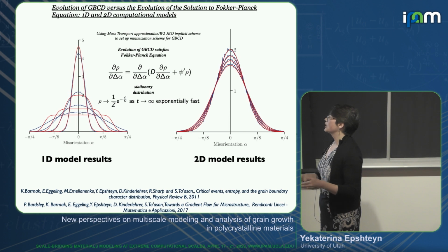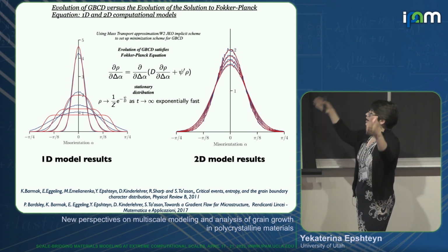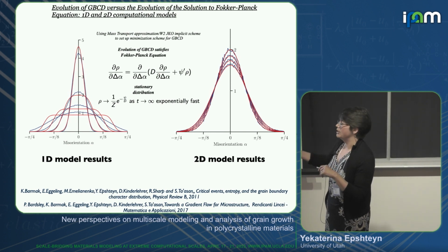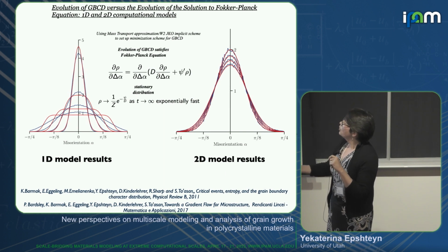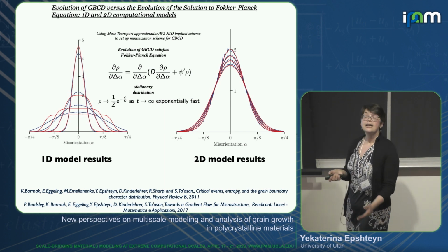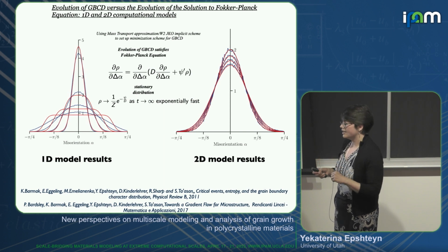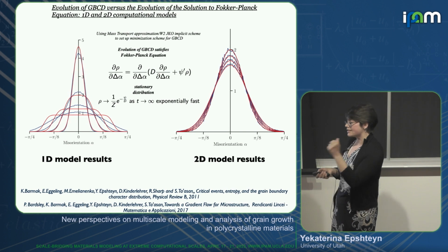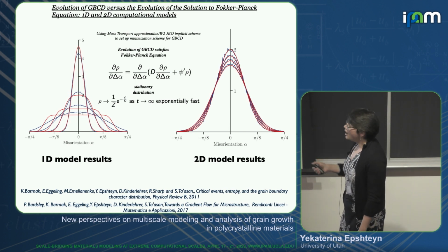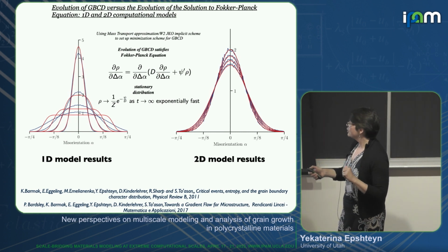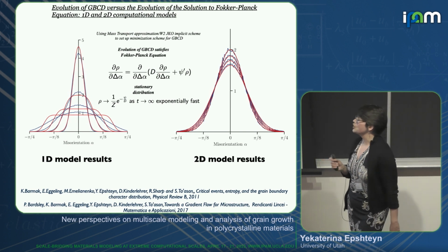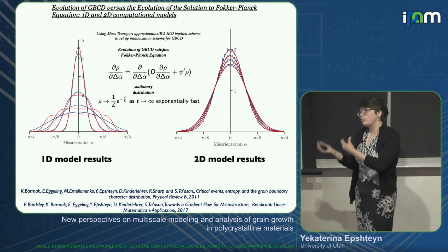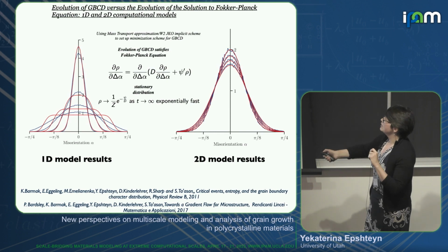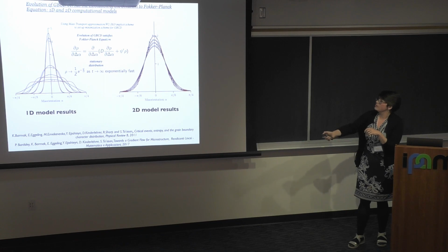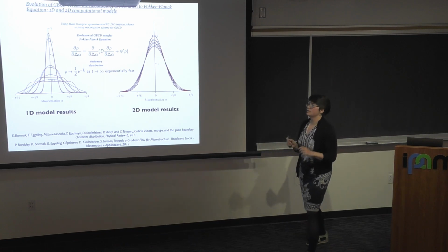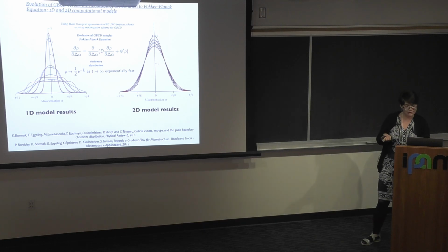And we decided to check, because we have a 1D coarsening model, and we have 2D large-scale simulations. We developed a theoretical model for evolution of GBCD using that 1D reduced model. We can check our prediction of the theory versus the empirical GBCD that we can extract from the 1D simplified model, and we can extract from 2D large-scale simulations. We compared evolution of empirical GBCD versus evolution of the Fokker-Planck equation, and actually the large-scale simulation model gave even better agreement. And we think it's because in 2D large-scale simulations, we really have triple junctions, and the simplified model oversimplified what happens at triple junctions. But that was an encouraging result.